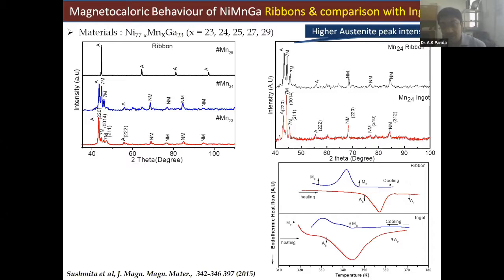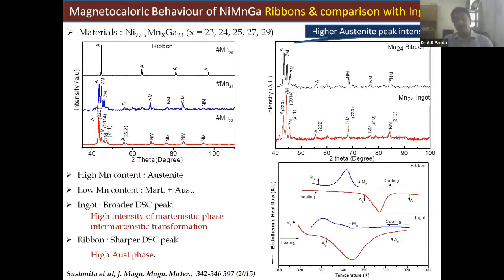And when you have a ribbon, the transitions are much sharper actually. But the reason is you have much smaller grain sizes. When you have a high manganese content, we have austenite. When you have a low manganese content, we have martensite plus austenite. And the ingot as usual has a broader DSC peak because we expect a lot of intermartensitic transformation. At the same time it has a much higher intensity of martensitic phase, while in the case of ribbon, we have a high austenitic phase. That's the reason you find a much sharper transition in the case of a ribbon.